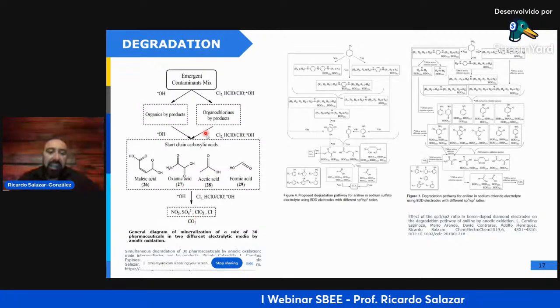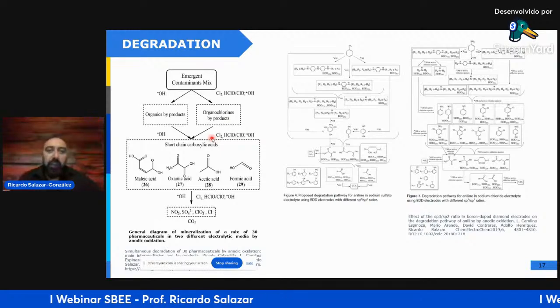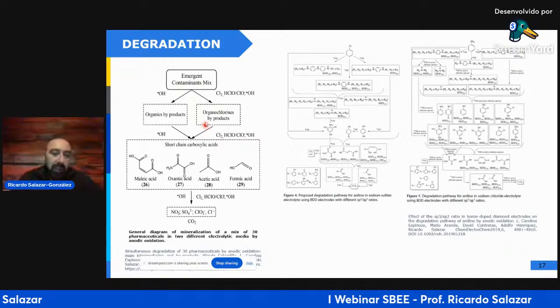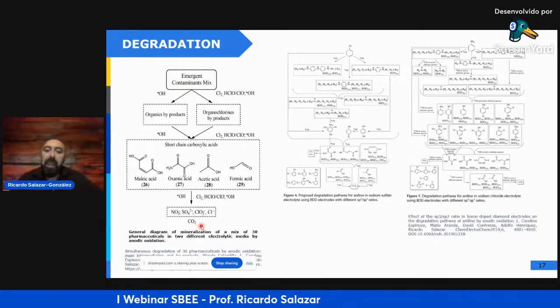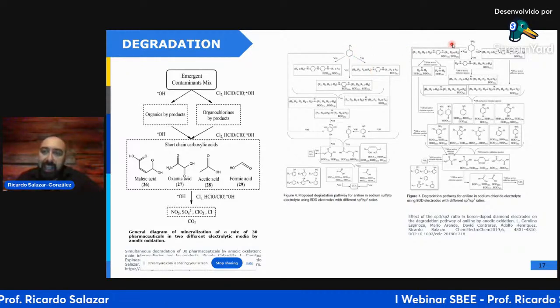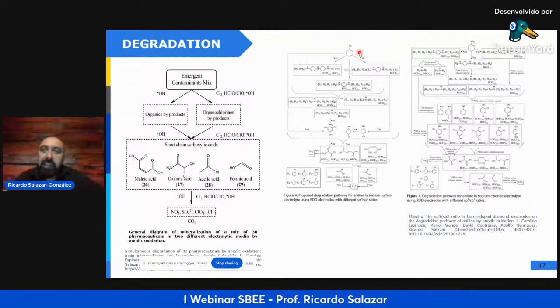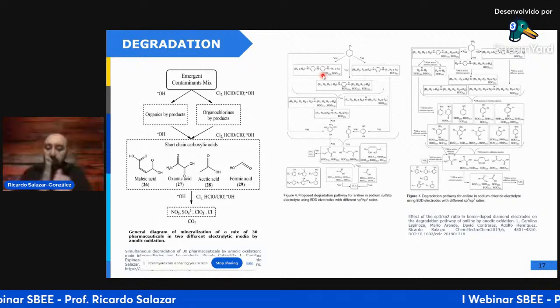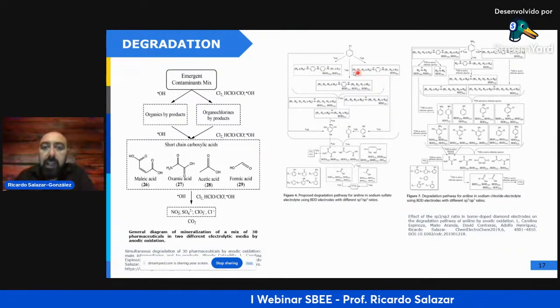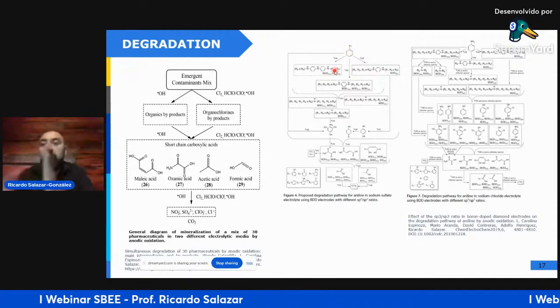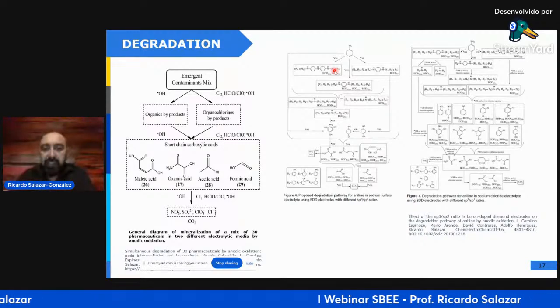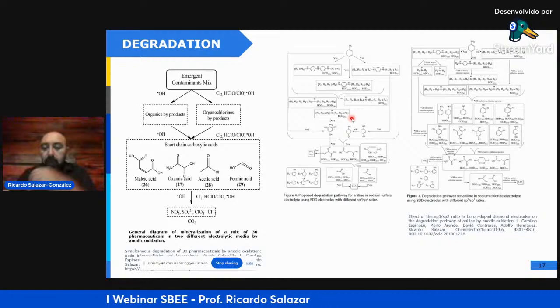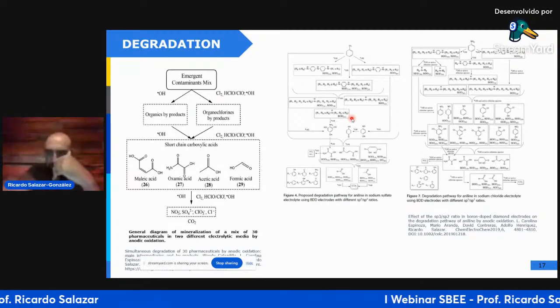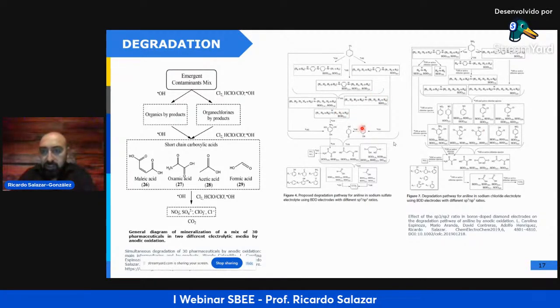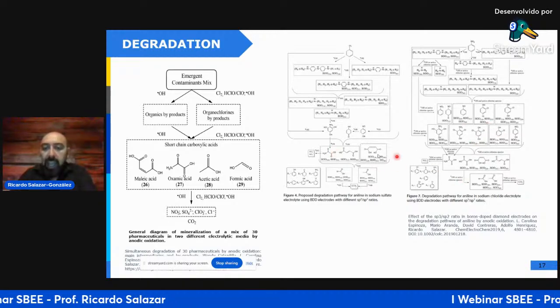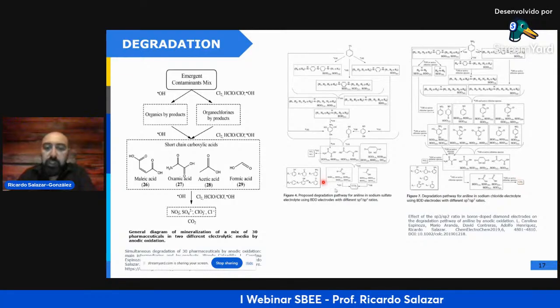In this work, we have a mixture of 30 compounds with different chemical characteristics, and all of them were completely mineralized to carbon dioxide. On the other hand, in a work where we studied the mineralization and degradation of aniline, an industrial compound, at the beginning of the electrolysis, we observed the formation of oligomers from the oxidation of aniline on the anode surface and the interaction with the hydroxyl radicals. But as the electrolysis continues producing hydroxyl radicals constantly during the process, these oligomers were destroyed, producing aromatic compounds and then carboxylic acids, up until the complete transformation to carbon dioxide.